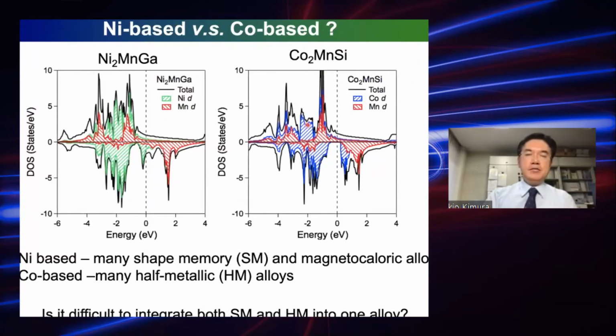So now we would like to compare the calculated density of states for Ni2MnGa and Co2MnSi, which are extensively studied. As I said, the very sharp peak is located near the Fermi energy in the minority spin channel like this. It can be a driving force of the lattice instability, which may be important for the Martensitic phase transition. On the other hand, in the cobalt-based alloys, which typically show a half metallic band structure, you have a large minority spin gap here.